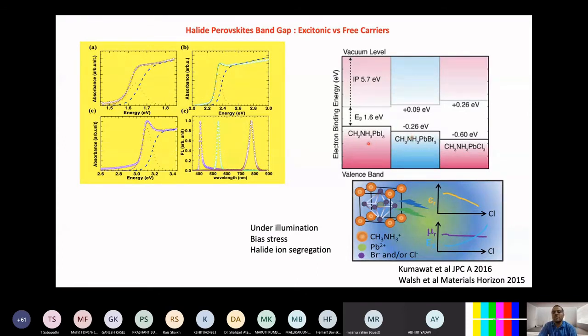Another interesting phenomenon which we have seen is, when you replace the halide ion from iodine to bromine to chlorine, you do not make a huge, significant difference in the conduction band minima, but there's a very significant change in the valence band maxima. So your valence band is being dominated by the halide ion, whereas your conduction band is not. So by changing the halide ion in the ABX3 family, your conduction band is not changing a lot, but your valence band is changing very significantly.